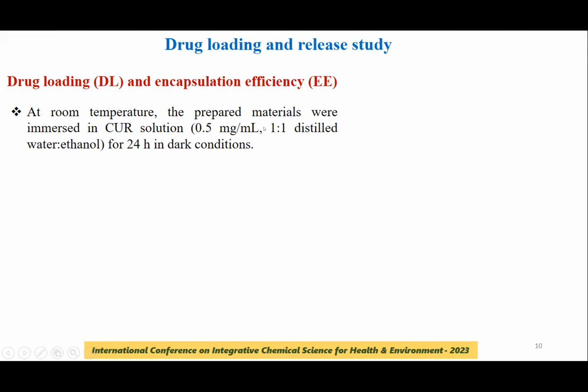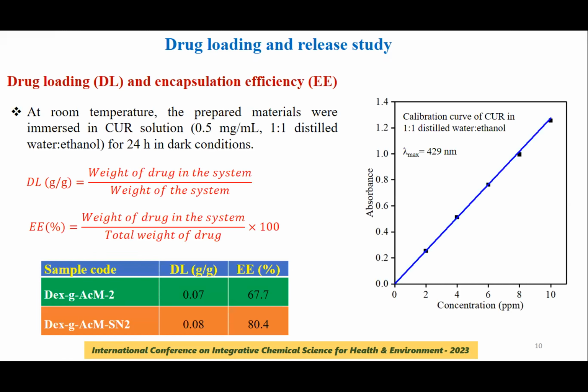Ethanol and water are used here because the drug is not soluble in water, so we use ethanol to ensure that it dissolves. But to ensure that the material swells so that the drug can diffuse inside the polymer matrix, we added water, which enhances the swelling and diffusion of the drug. Then, using a calibration curve, drug release efficiency and encapsulation efficiency were calculated, where the nanocomposite hydrogel shows higher swelling, drug loading, and encapsulation efficiency.